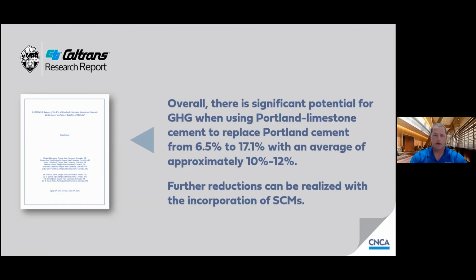And then additionally, regarding greenhouse gases, this study found that the reduction in greenhouse gases from using Portland limestone cement could be between 6.5% and 17.1%, with an average of 10 to 12%. We're generally mentioning 10%. That's what we're seeing as probably the most likely scenario. But due to the synergies of this material with the supplementary cementitious materials, like I mentioned earlier, there's a lot of opportunity here for further reduction, utilizing the tools that we have available to us in terms of mix optimization and supplementary cementitious materials.